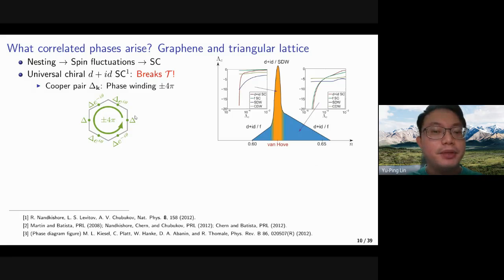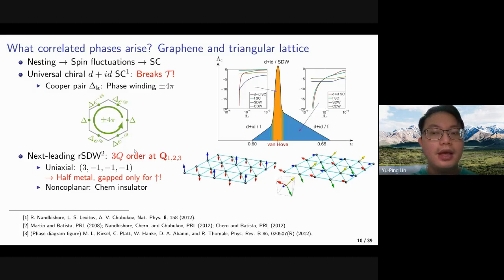So how does it break it? Actually, it breaks it by having a Cooper pair which winds for plus or minus 4 pi in terms of its phase when we go around the Fermi surface. So this kind of phase winding breaks the time reversal symmetry. And because it is plus or minus 4 pi, it corresponds to the d-wave form factor. Meanwhile, we could also have the real spin density waves, which are the next leading instability.